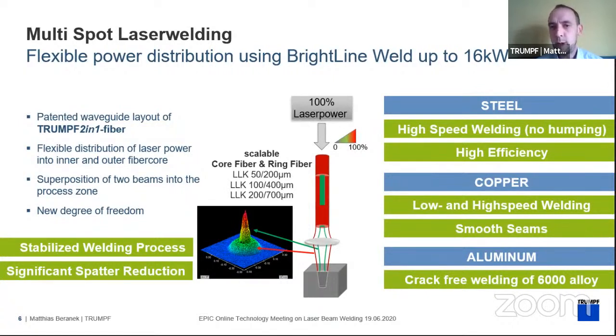In our case, we call it Brightline Weld. That is the Trumpf name, and we've also originated that technology up to 16 kilowatts. As you can see, we will use a 2-in-1 fiber guide. That practically means you will be using 2 spot sizes at the same time with a certain power distribution at different sizes. The main effects are most notably a stabilization of the welding process, which means the keyhole dynamics, and so on. And this results typically in a significant spatter reduction, minimization.